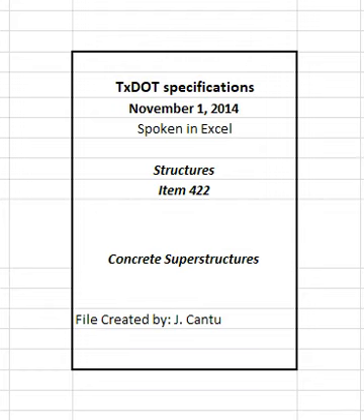4.9 Removal of forms and false work. Forms for vertical surfaces may be removed after the concrete has aged 12 hours after initial set provided the removal can be done without damage to the concrete unless otherwise directed. Remove forms for inside curb faces and for bridge rails whenever removal can be done without damage to the curb or railing.